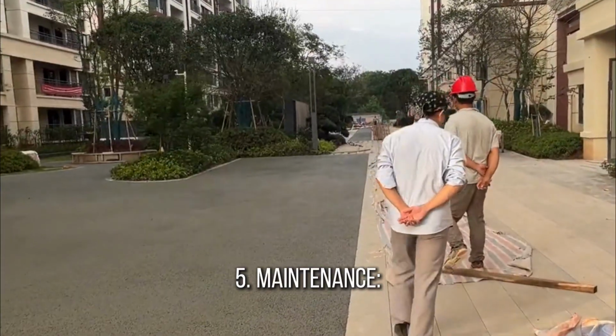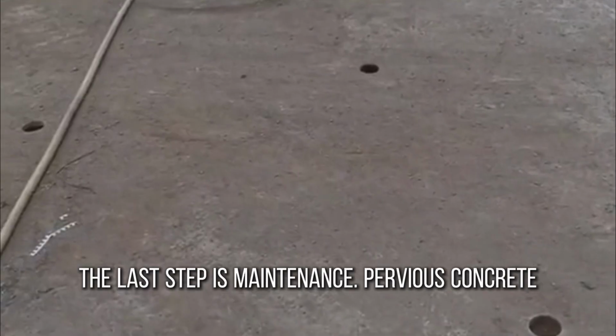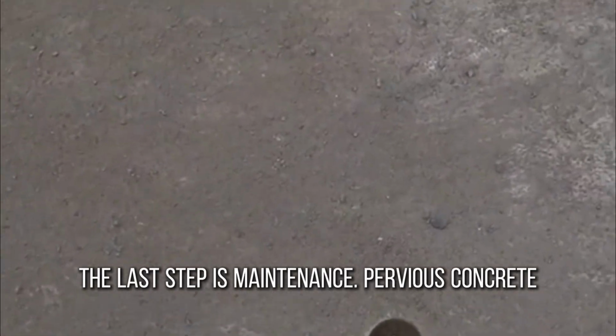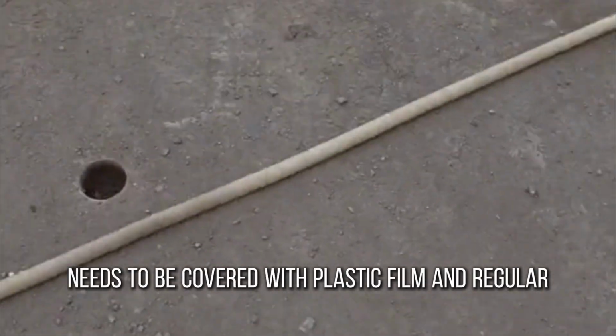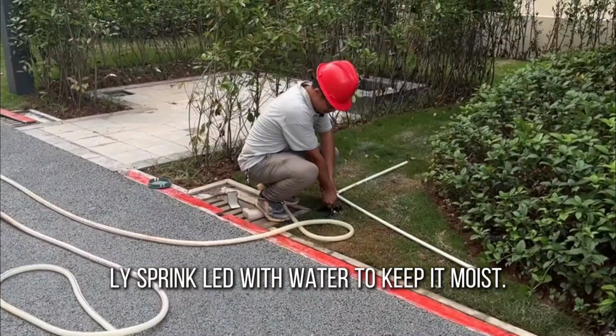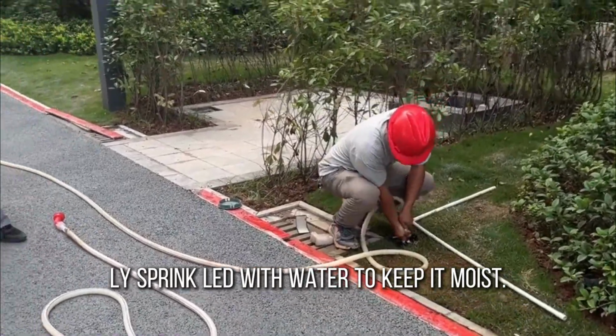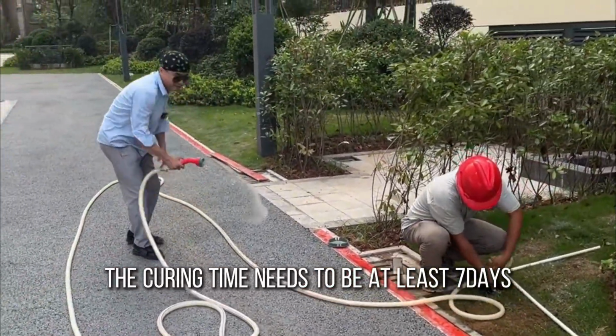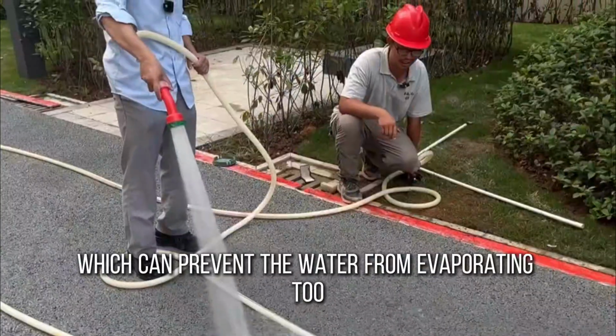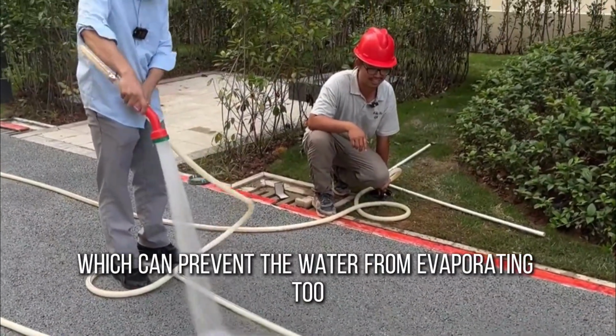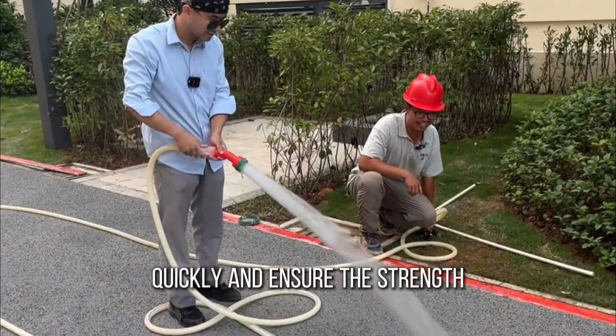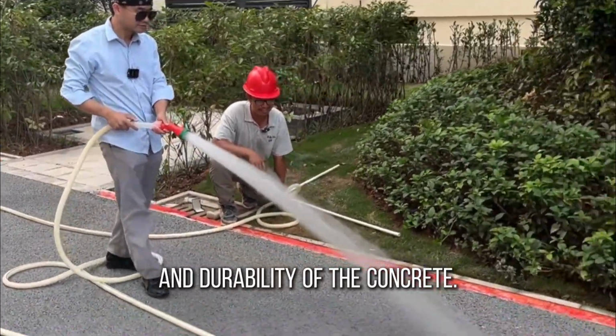5. Maintenance. The last step is maintenance. Pervious concrete needs to be covered with plastic film and regularly sprinkled with water to keep it moist. The curing time needs to be at least 7 days, which can prevent the water from evaporating too quickly and ensure the strength and durability of the concrete.